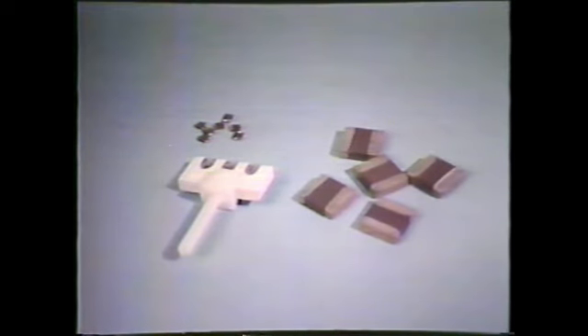For most jobs, you'll use a rosin flux core solder of 63% tin and 37% lead. This is identified on the spool as SN63. If a lower melting temperature is needed, then a 2% silver-bearing solder should be used. Silver solder is very expensive, so don't use it unless necessary. Components with silver in their terminations, such as chip resistors and capacitors, and ceramic connectors, must always be soldered with silver solder. This prevents leaching of silver from the termination.